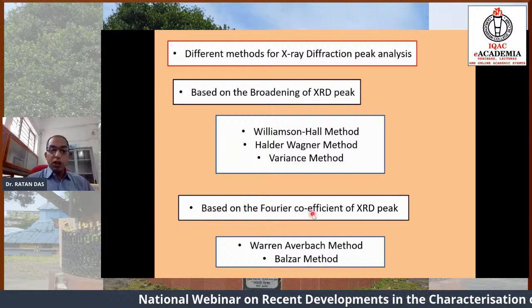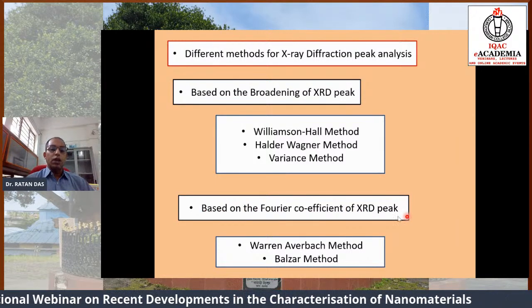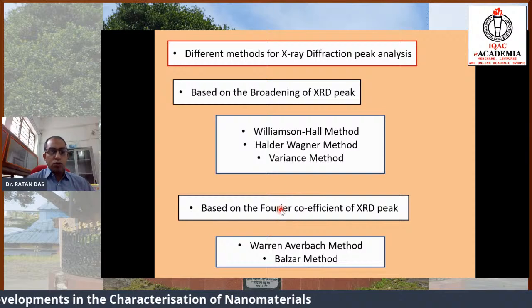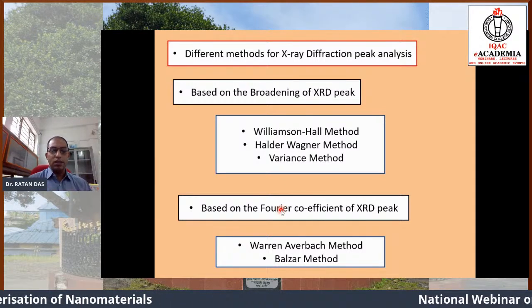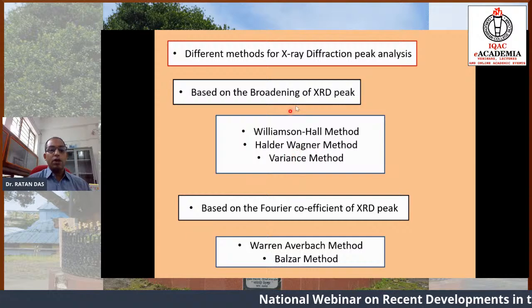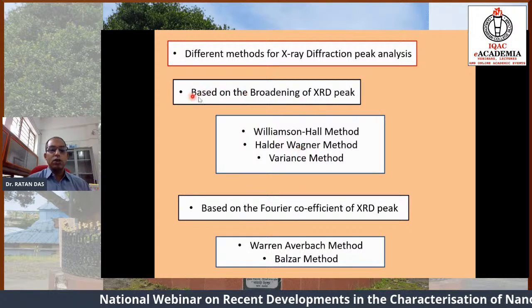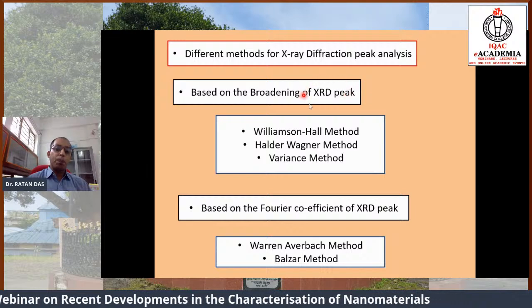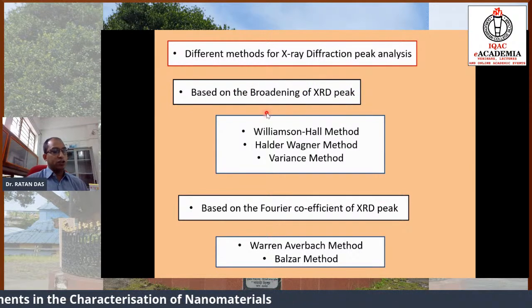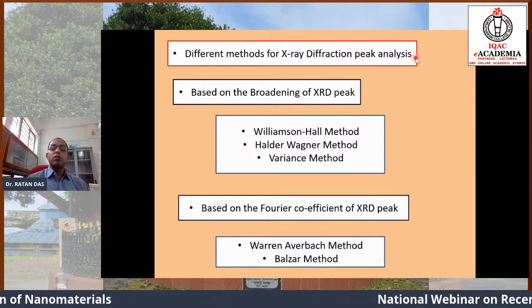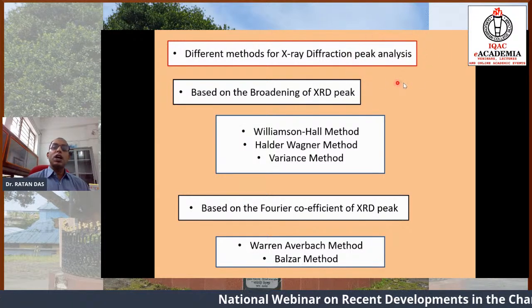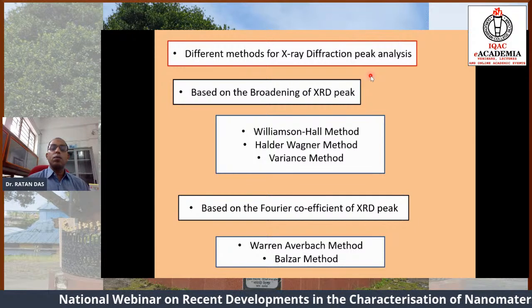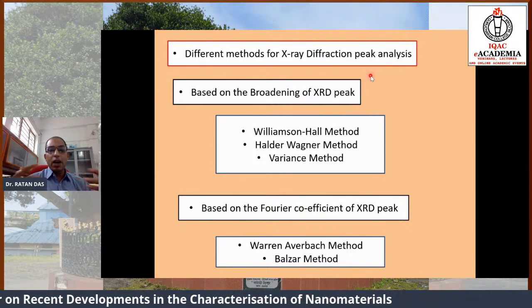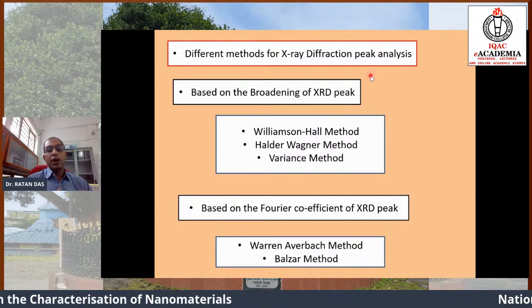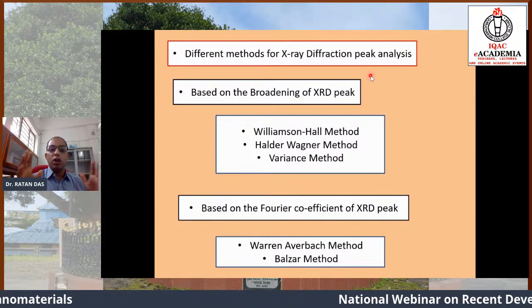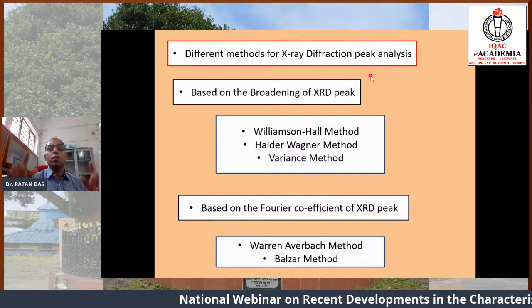But based on the Fourier coefficient of the X-ray diffraction peak, I shall say later also in my slide, but at this particular time, in this related topic, I want to tell you that the X-ray diffraction peak may be analyzed using the broadening of the X-ray diffraction pattern. But in the peak profile analysis, what we do generally, we make some pattern of the peaks actually. What is the pattern? We match a particular function with the peak.